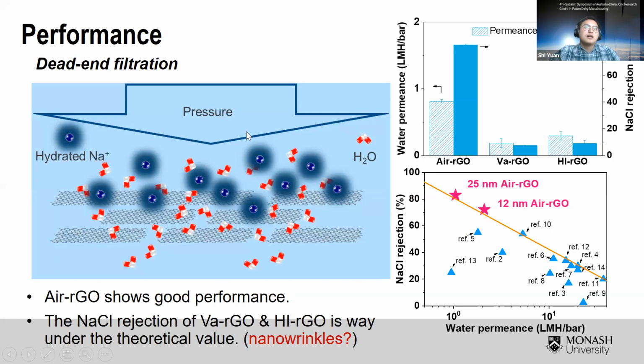We investigated their performance in a pressure-driven process with 1 gram per liter sodium chloride solution. As illustrated by this figure, RGO membranes with smaller interspacing exhibit smaller water flux. However, low sodium chloride rejection is also observed. By contrast, Air-rGO with larger interspacing shows effective sodium chloride rejection. So this phenomenon further indicates that there must be some other channels.